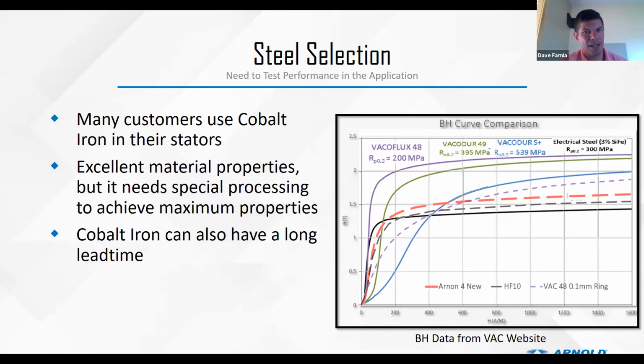It can. With silicon steel, in our testing, when we laser cut laminations or stamp a silicon steel lamination, you'll want to do a stress relief anneal. When we laser cut a silicon steel, usually it's not necessary. With cobalt iron, we're always very careful about speccing the stress relief anneal, because without it, our properties can really be degraded, whether it's laser cutting or stamping.